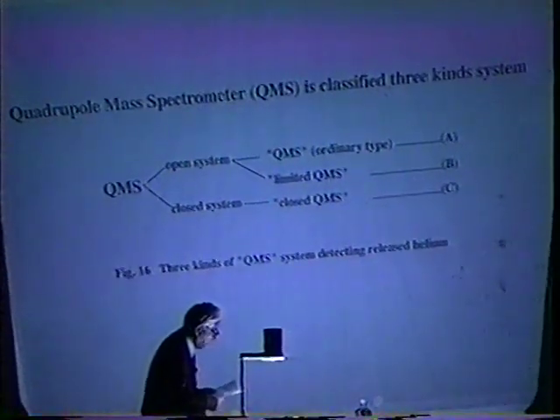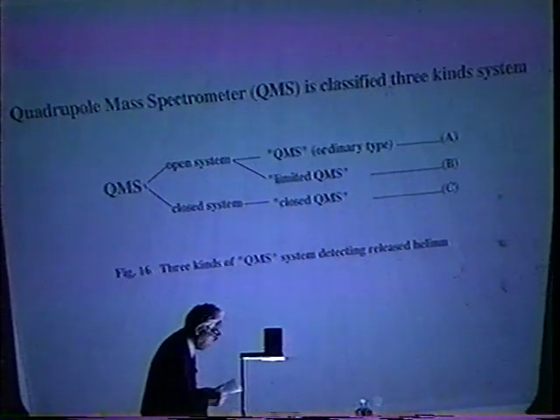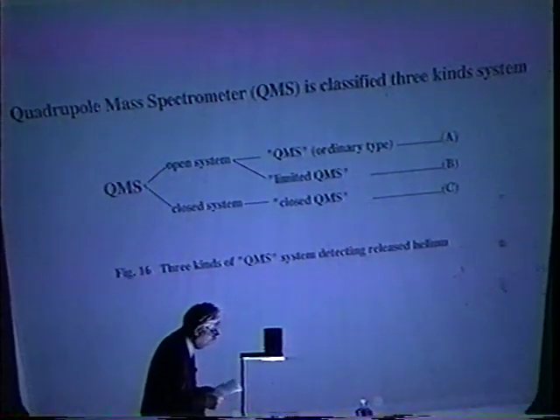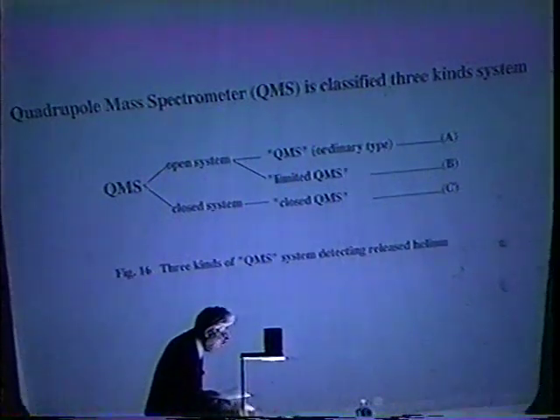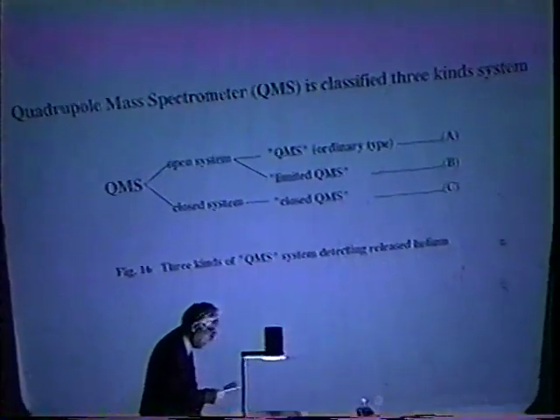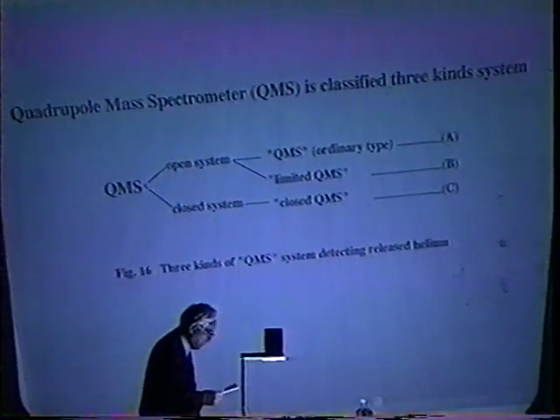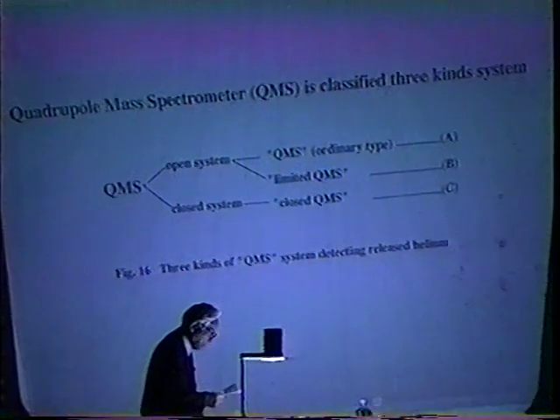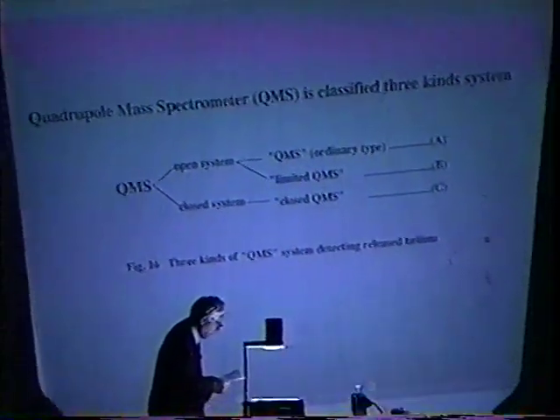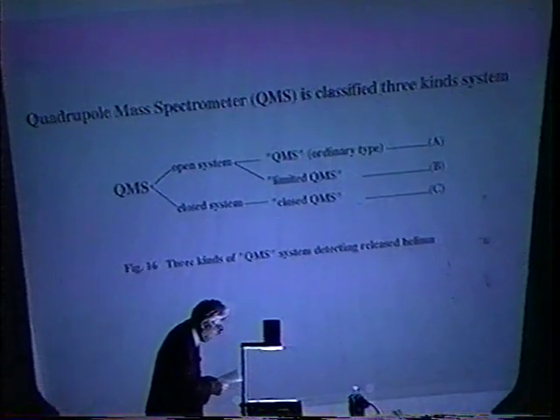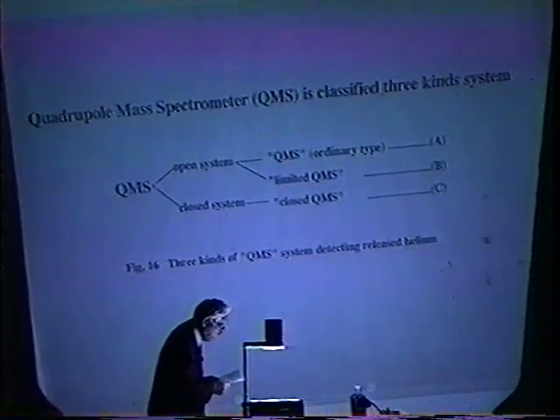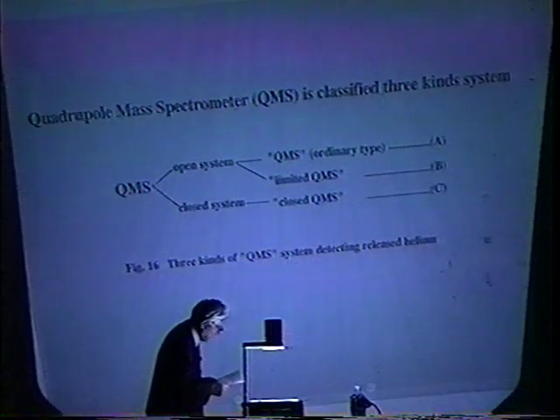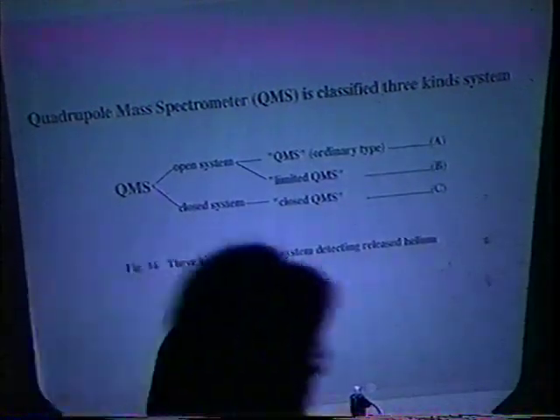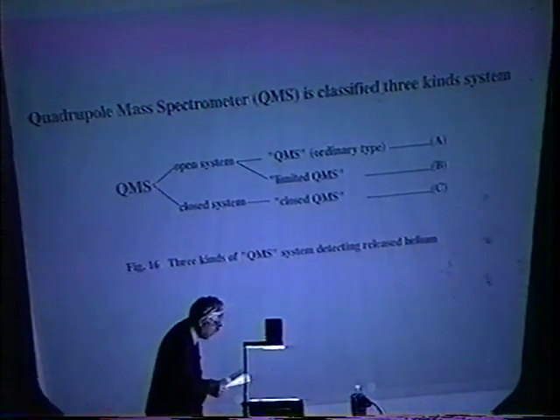Namely, we developed the B and C types. B type has fine control of the back pressure of the QMS. We call it the limited QMS, by which we obtained many excellent data. Thus, we arrived at the final stage, the closed QMS, which is constructed of only the sample vessel, getter, and the QMS. In other words, the closed QMS is completely separated from other systems.